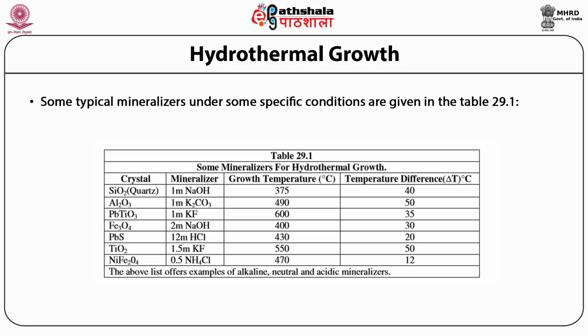PbTiO3, for which the mineralizer is 1m KF, growth temperature is 600 degrees centigrade, and the temperature difference is maintained at 35 degrees centigrade. For the crystal Fe3O4, the mineralizer used is 2m NaOH. The growth temperature is maintained at 400 degrees centigrade, and the temperature difference delta T is maintained at 30 degrees centigrade. For the growth of PbS, that's lead sulfide, the mineralizer is 12m HCl. The growth temperature is 430 degrees centigrade, and the temperature difference delta T is maintained at 20 degrees centigrade.